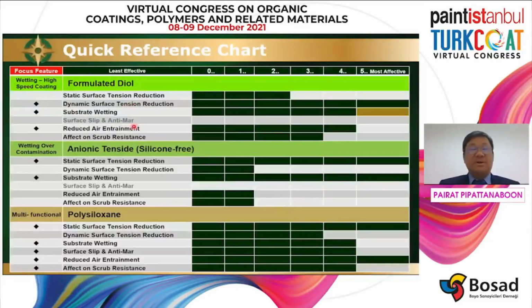This is just a summary or quick reference in terms of chemistry, the industry benchmarks in the market. Anionic surfactant, that we're talking about, helps to improve static surface tension and also gives you substrate wetting, right? Leveling and flow improvement. You don't get anti-slip, anti-mar, and air reduction is not there.